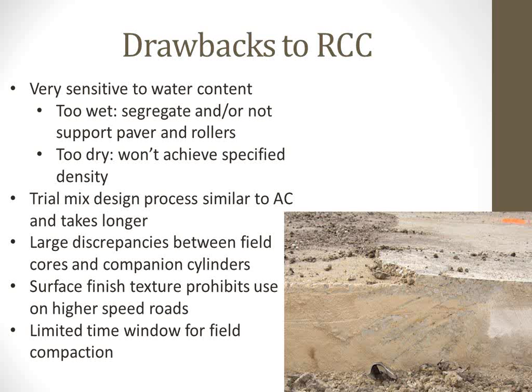Some of the drawbacks are its moisture sensitivity. Since you're designing it based on a maximum density from the proctor test, any deviation from the optimum moisture will either cause the mix to segregate or it won't be able to be compacted to a certain level. The mix design is similar to asphalt. It's pretty involved compared to concrete, where it's a simple step-by-step procedure. First, you have to choose your aggregate structure, then you also have to do the proctor test, and then depending on whether or not that worked or not, redo it.